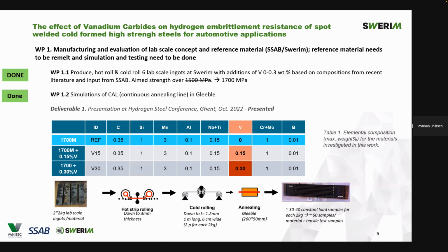Here we can have a look at the materials that we investigated in the table that you see here. On top, the blue one is the reference material without vanadium, and then we have 0.15 and 0.30 weight percent vanadium added to the other two materials. The strength obtained for those materials is about 1700 megapascals. After production, those materials were processed in Gleeble.